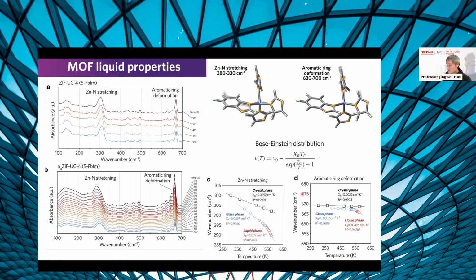But everything follows the physical chemistry process. So you can use entropy to reduce the melting temperature. Increasing the entropy will reduce the phase transition temperature because of the Gibbs equation. That can be done either by increasing the complexity of the system, introducing a composite, or, let's say, a host-guest composite structure for the MOF. I think Tom has done some study by introducing imidazole-based ionic liquid into the framework, which can significantly make some previously unmeltable MOF meltable. I see. So still an energy field to play.